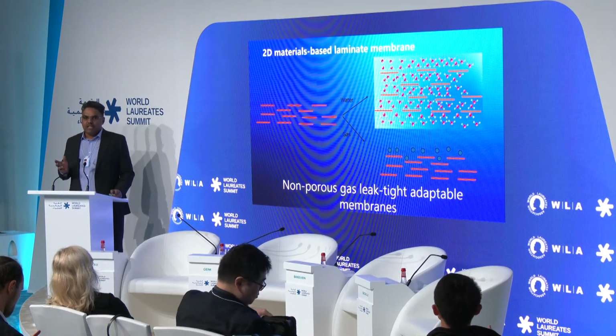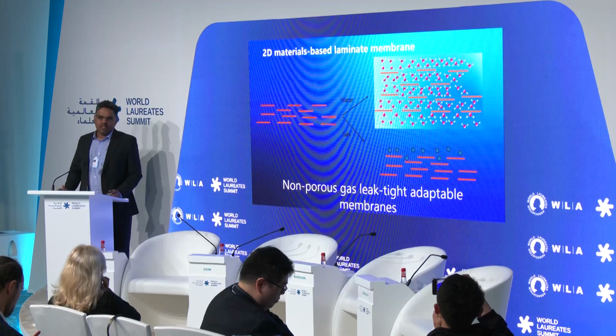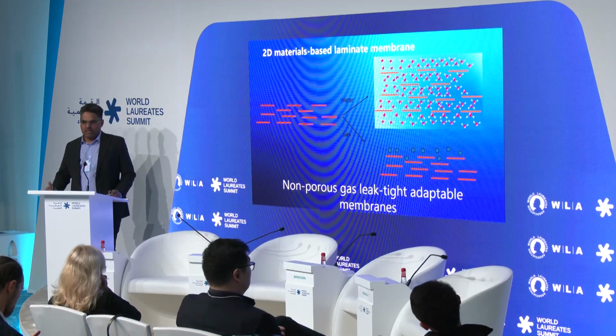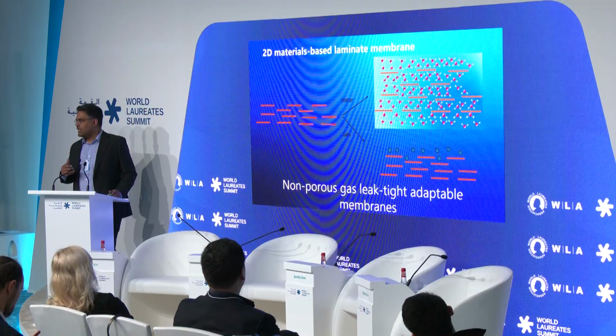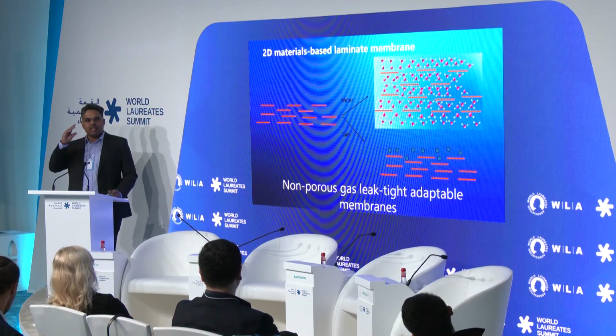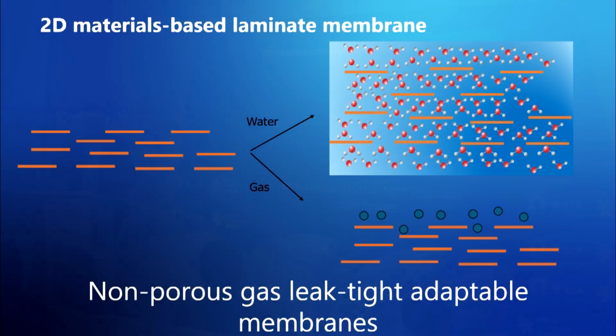Such membranes are typically impermeable to gases but permeable to liquids. When you expose them to gases, these layers are tightly packed and nothing can go through, but when you expose them to vapors or liquid, the membrane self-expands. This is called membrane swelling, and liquids go in between the layers and permeate. The selectivity is controlled by the distance between the layers, and we call it an adaptive membrane because depending on the environment to which it is exposed, the properties can change.